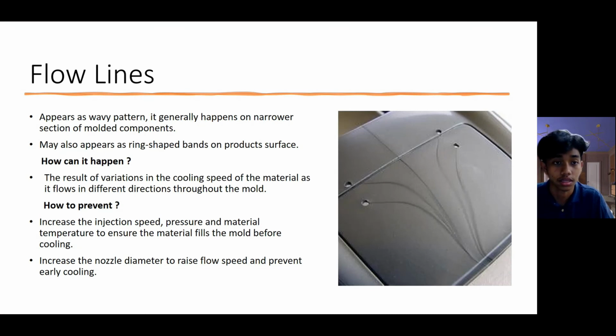So the first defect is flow lines. Flow lines appear as a wavy pattern. It generally happens on narrower sections of molded components. It also may appear as ring-shaped bands on the product surface. How do flow lines happen? They are the result of variations in the cooling speed of the material as it flows in different directions throughout the mold.